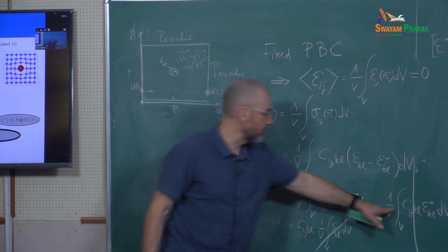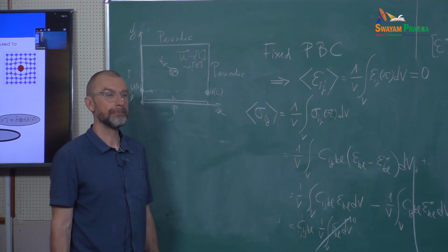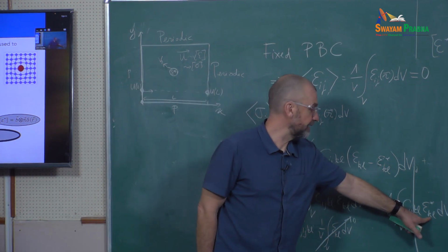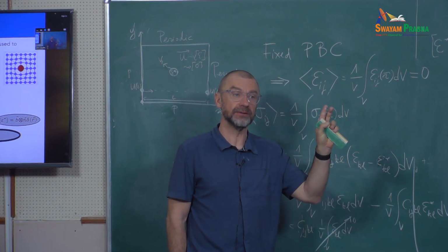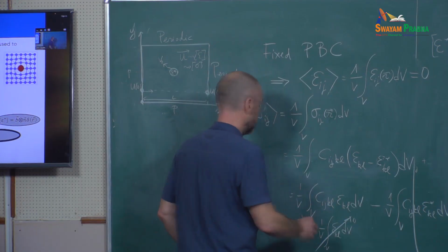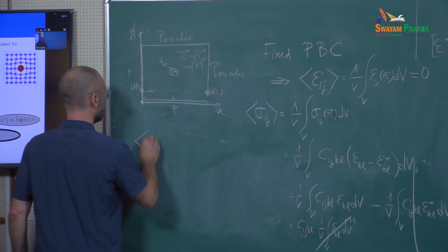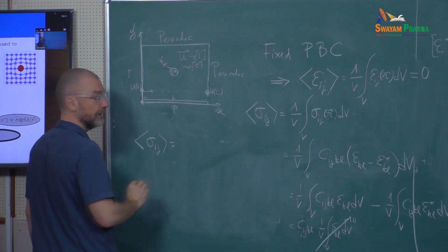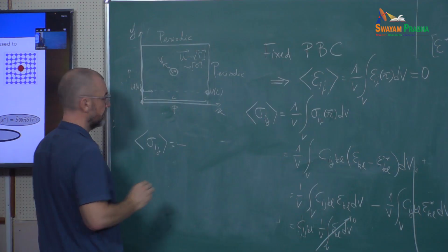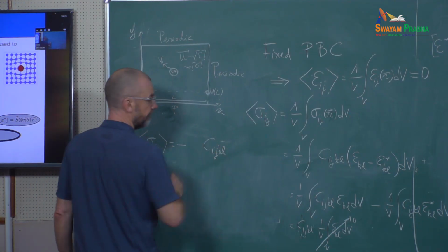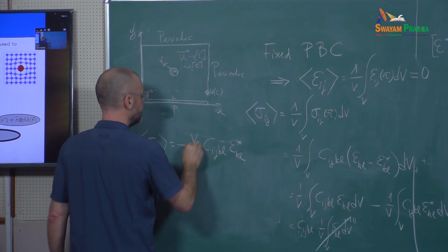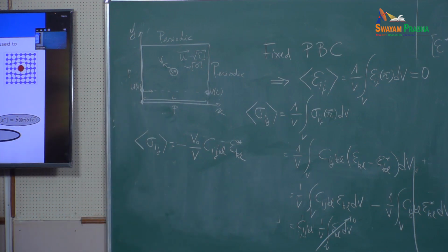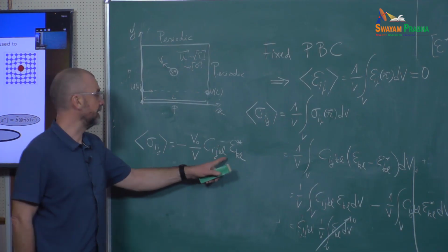And now this term, what is it equal to? So epsilon_kl star will be non-zero only inside the precipitate, where it is constant. So the integral will give you directly, there's a minus, there's C_ijkl, exactly, epsilon star_kl, V0 over V. Yes? Now I can invert that.